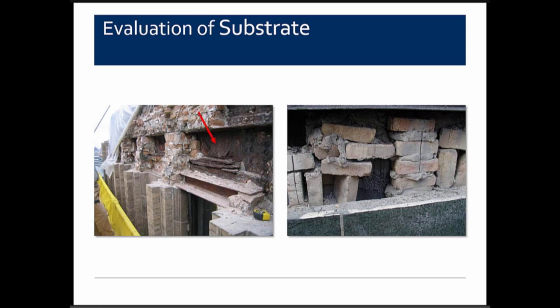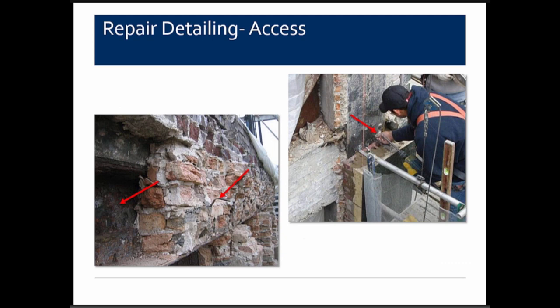Evaluating the substrate is important: if you need to stabilize units with pins or straps rather than a full repair, you need to know where the steel is so you don't pin a unit thinking you're hitting brick backup when you're actually hitting a steel beam — making the pins useless. Poor backup, such as voids from incomplete grouting during original construction, also renders pins ineffective. Knowing backup conditions and steel location is essential when you go to do repair detailing.